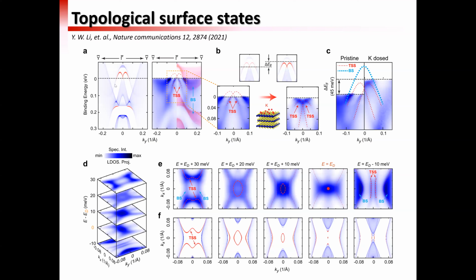And according to our calculation, at the gamma point, between the bulk conduction and valence band, there's an M-shaped topological surface state inside this tiny gap. This is still difficult to see, because if you notice the scale, this is less than 0.1 inverse angstrom. So in this case, we also turn to laser ARPES so that we can have a higher momentum resolution as well as energy resolution.